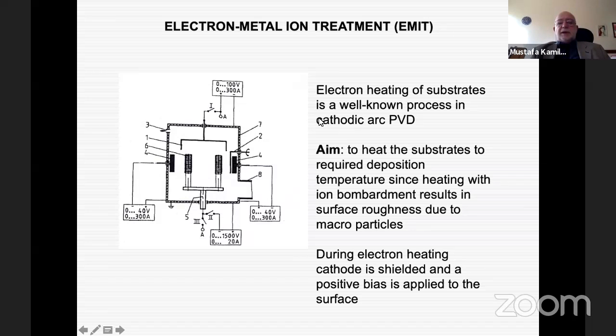So there are a few studies in the literature that utilize these electrons for heating of the substrates. What they do is they cover the surface of the cathode, and then instead of applying a negative voltage to the substrate, they apply a positive voltage, so that the electrons that are created in the cathodic arc plasma specifically come to the surface of the substrate materials. That will lead to heating of the substrates. So this has been a method that has been used in some cathodic arc PVD systems, but mainly for heating the substrate with electrons instead of using ions.